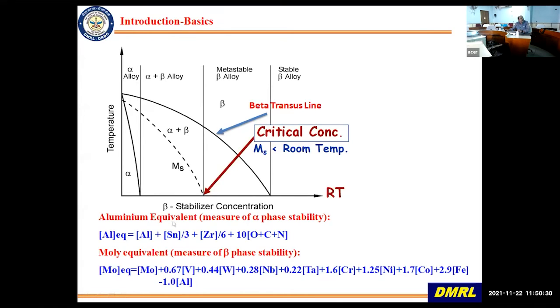And then there is another one which is known as aluminium equivalent. That is a measure of alpha phase stability. And in this, there are only a few elements. Aluminium, as you can see, is one of the main stabilizers. Tin and zirconium, which are neutral, come in. And oxygen, carbon, and nitrogen are also alpha stabilizers. Now, if you look at this pseudo-binary phase diagram, here you have the single phase alpha region. Then you have the alpha plus beta region in between. And then above this temperature line, you have the beta phase.